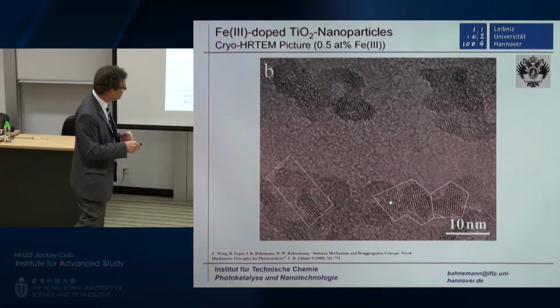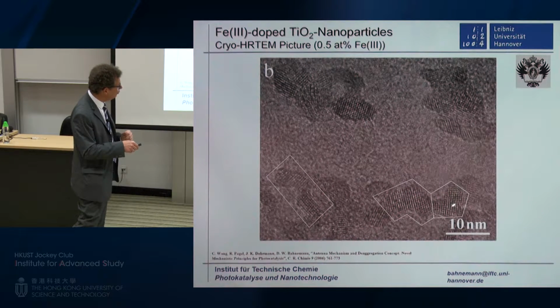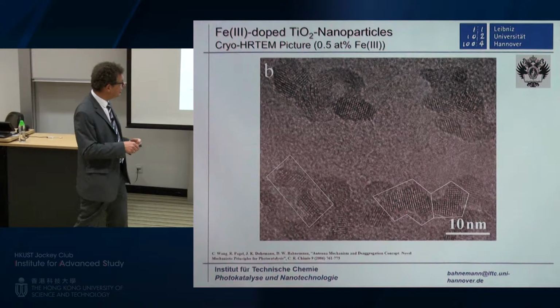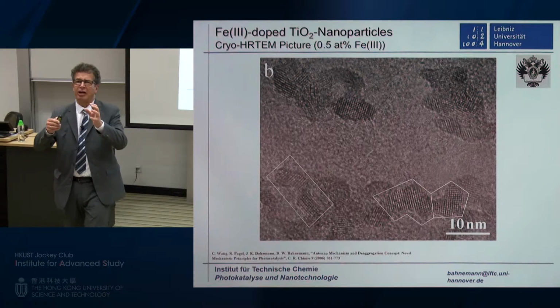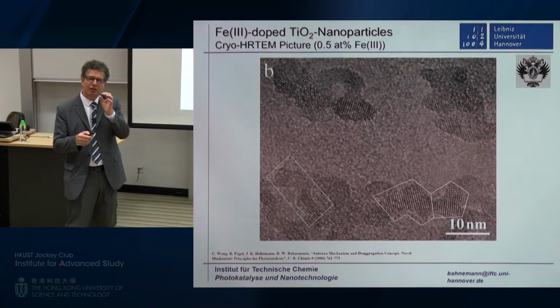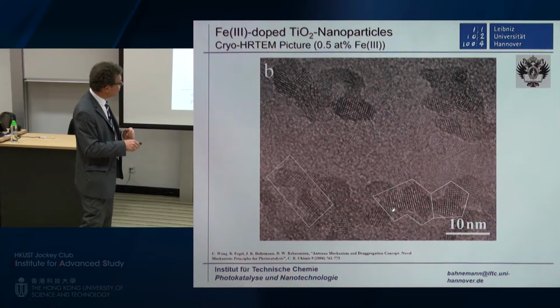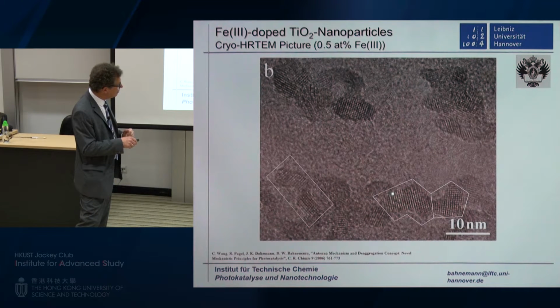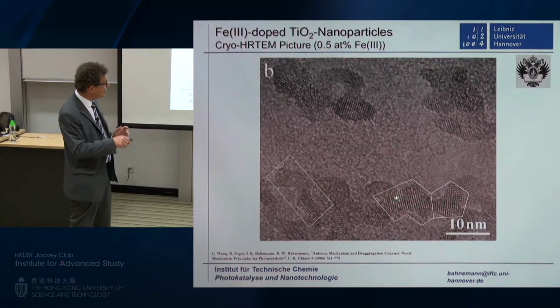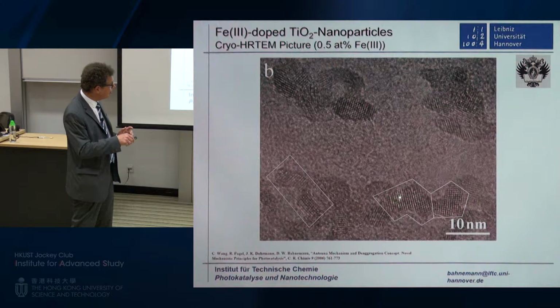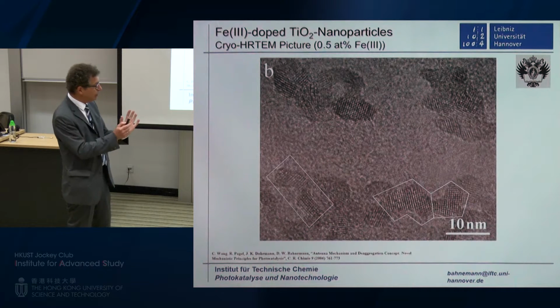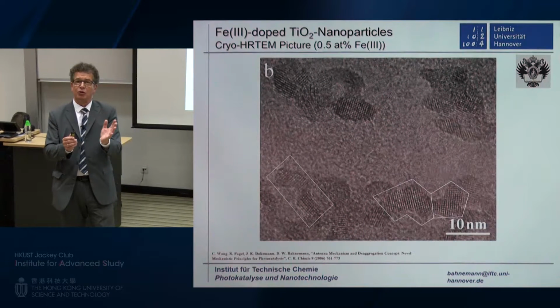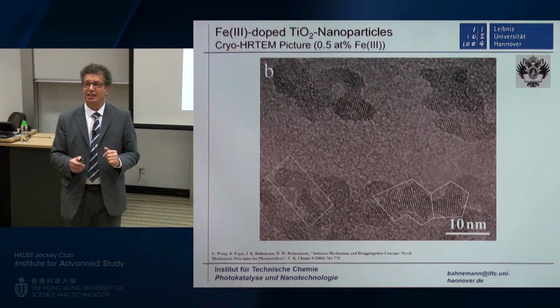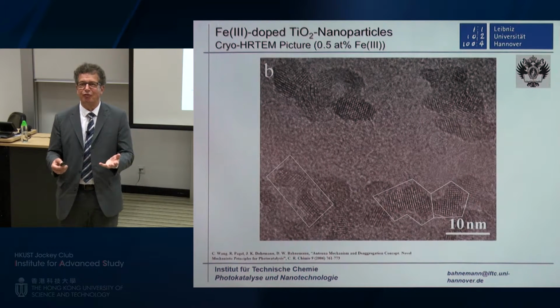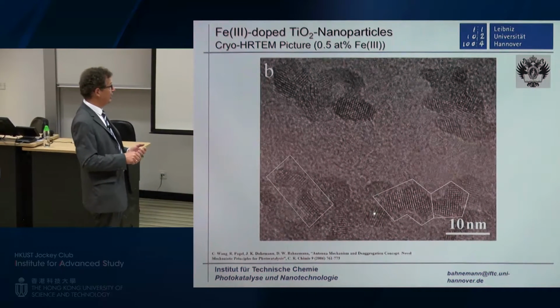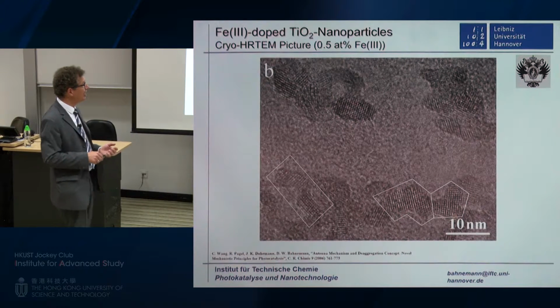But what you see also is that these particles tend to form aggregates. And these aggregates are not formed in an arbitrary way, but in a very elegant way. These particles seem to see the atomic planes of the neighboring particle. What you are forming here is one particle, second, third, fourth, and the atomic planes are parallel to one another. So what you're forming actually are little nanowires. But you are not forming this. The material forms it itself. The material just likes to be like that. That seems to be energetically the favored state.